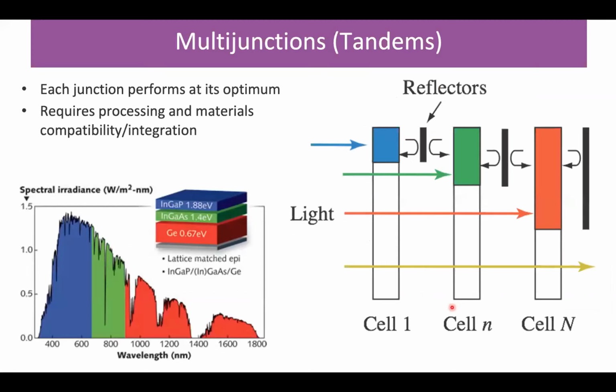But then the other thing we can do, since with one junction we clearly have to make some compromise between where we harvest and where we let photons through, is that it makes sense that one way to maximize the efficiency is to not make the compromises in the same way, but have multiple subcells that would pick off each different wavelength. And here you see a triple junction system where the top cell collects the blue, but it passes the longer wavelengths. You have another absorber behind it that's picking off the green. And again, the longer wavelengths still go through, but then you pick those off as well. And using this kind of approach, you can increase your performance considerably.